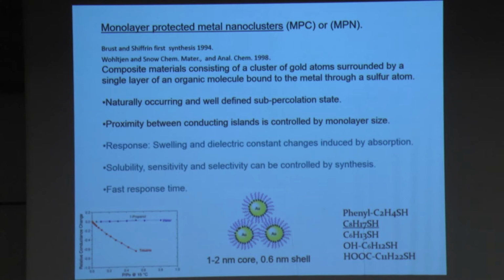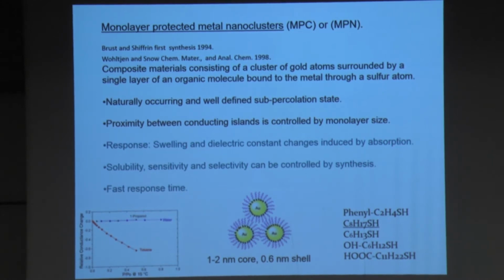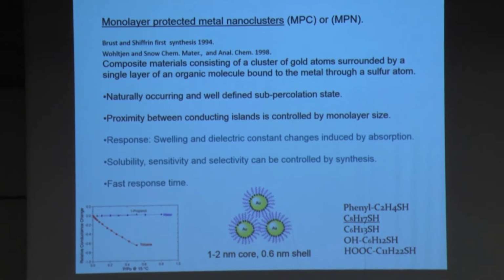These are composite materials consisting of clusters of gold atoms surrounded by a single layer of organic molecule bound to the metal through a sulfur atom, mostly. They provide a naturally occurring and well-defined subpercolation state. The proximity between the conducting islands is controlled by the monolayer size.